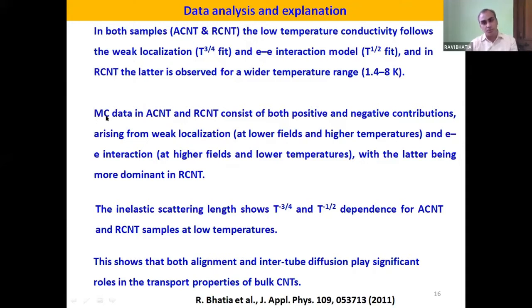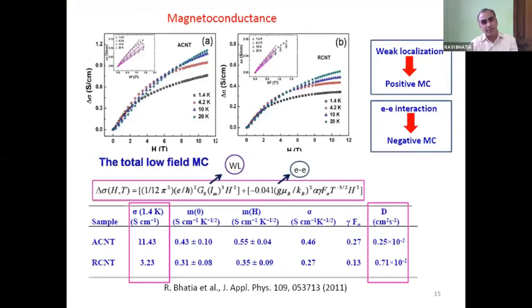Magnetoconductance data is also in agreement with this particular statement that electron-electron interaction and weak localization in the carbon nanotube are present, and the metallic behavior is observed in the two samples. The diffusion of the charge carriers is also observed. In the case of the random sample, it is a little bit more than the aligned sample.